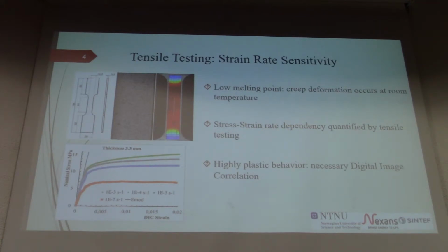So we performed some initial tensile testing, and that is made basically by cutting open the cables, unfolding the sheeting and producing dog-bone specimens from it. We had to use digital image correlation because it's extremely ductile and it's impossible to trust the displacement of the clamps. Performing this testing from 10^-7 s^-1 strain rate to 10^-3, we have a clear influence of the strain rate on the stress reached, and that is caused by the creep that is active. These are room temperature tests, but these alloys melt around 300–320 degrees Celsius. So even at room temperature, we are